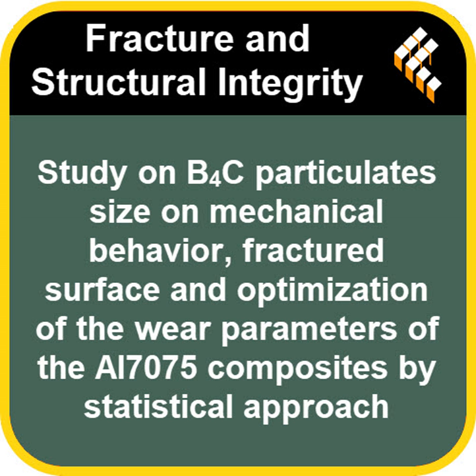What did the fracture surfaces look like under the microscope? Did that confirm this? Oh, definitely. The visual evidence was quite striking. When they looked at the broken surfaces, the composites reinforced with the larger micro-sized particles showed multiple cracks, a brittle kind of rupture. It looked like things had just snapped. Consistent with the particles cracking. Exactly. But in stark contrast, the composites with the smaller nano-sized particles showed a fracture surface that looked almost ductile. You could see these little dimples on the reinforcement particles. It indicated a much more resilient, tougher failure mode, not just snapping, but stretching and tearing a bit first. That's a really clear visual difference. Powerful evidence for the nanocomposites being more robust.